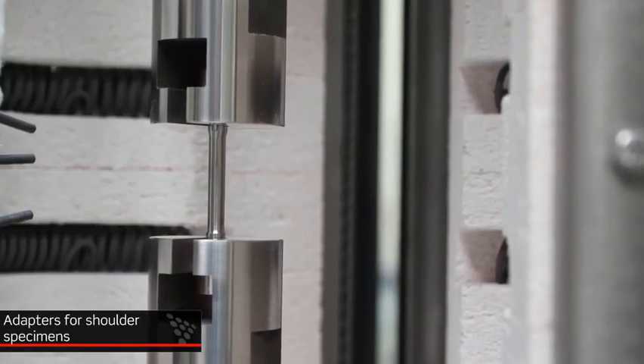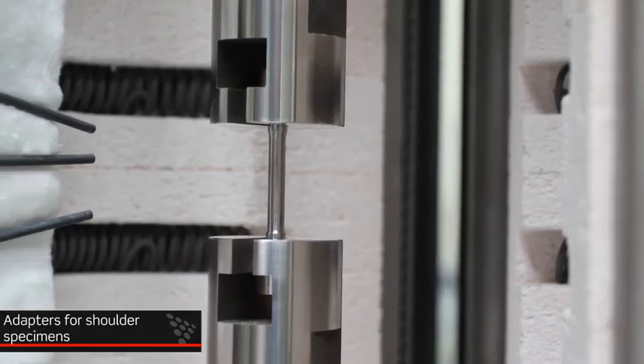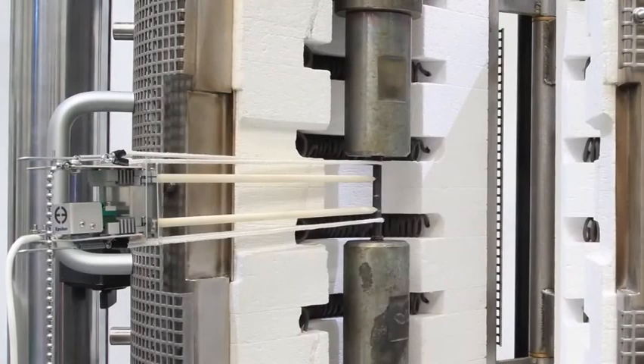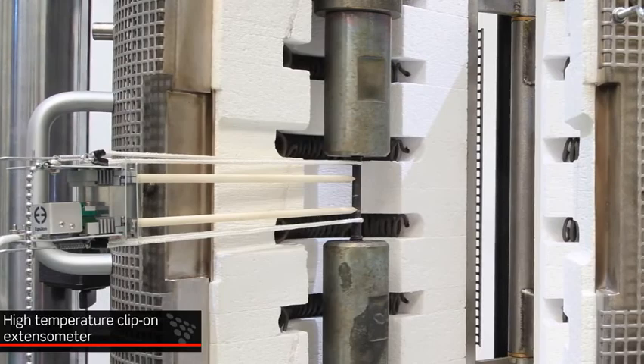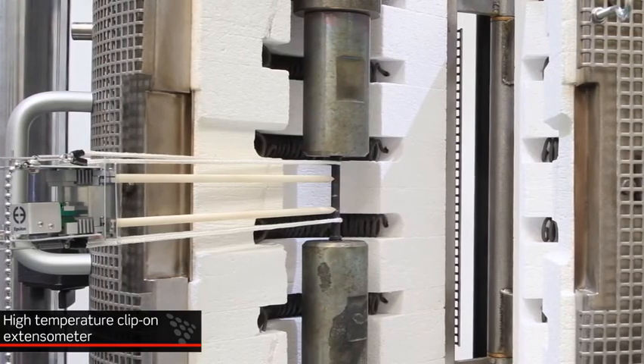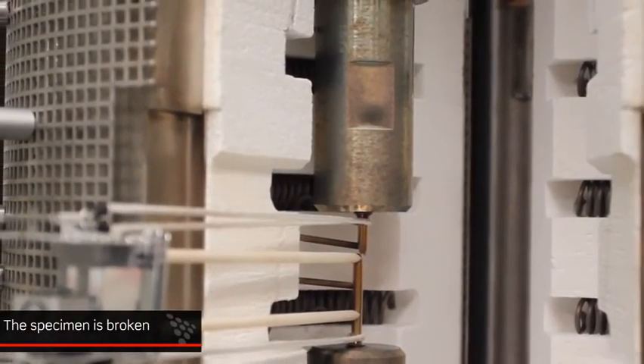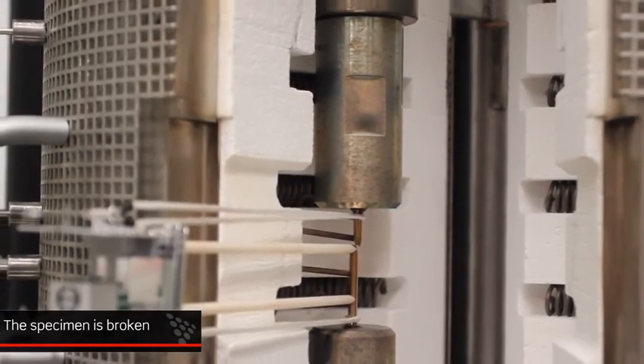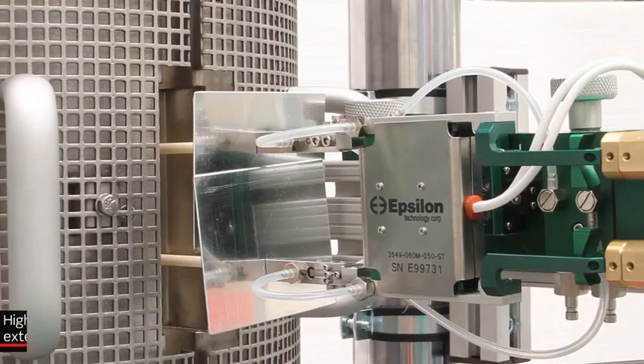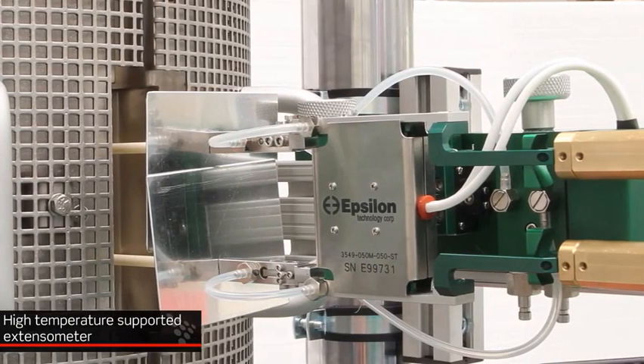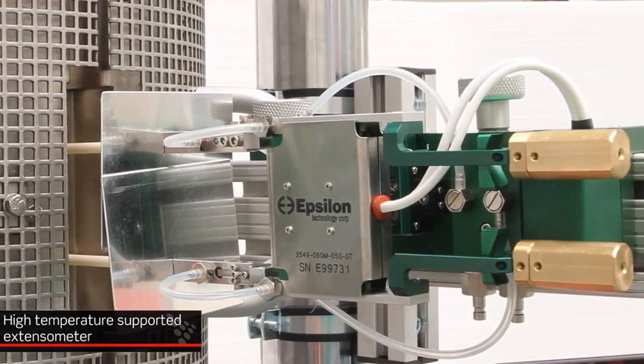And these are the adapters, and after that you will see at the end of the test that the specimen will be broken. You see how the extensometer is attached to the specimen. And now the specimen is broken, and with this the experiment ends, and you will have the data from which you can calculate the minimum creep rate.